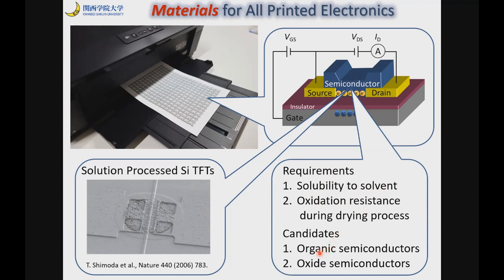For the solubility, organic materials are very appropriate because organic molecules can be easily dissolved into the solvent. But after patterning, we need to dry the patterns. During this drying process, organic materials tend to be oxidized. Therefore, organic semiconductors don't have the oxidation resistance after patterning during the drying process. Therefore, we are interested in the oxide semiconductors. In this case, oxide cannot be dissolved into the solvent, but metal complex can be dissolved into the solvent. And after patterning, we can make the heat treatment for oxidation. Therefore, we are interested in the oxide semiconductors.